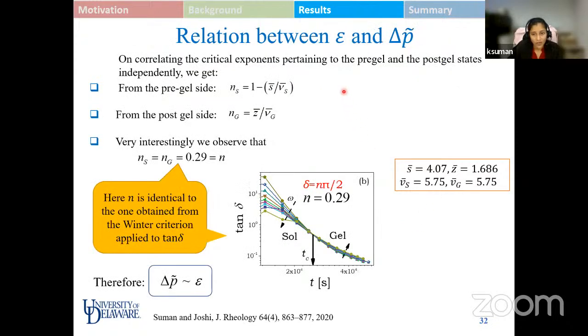With these exponents in hand, we use the laws of linear viscoelasticity, and doing some mathematical calculation, we end up with simple hyperscaling laws, which are relationships between many exponents. So n is the relaxation exponent, and these parameters are the exponents with which the viscosity and relaxation timescale evolve in the pre-gel state. With these hyperscaling laws in hand, we calculate the value of the relaxation exponent in the pre-gel, which is S, and in the post-gel, the G region. And we calculate it to be identical to 0.29, which was independently obtained in the oscillatory experiments. Such a validation of 0.29 using the scaling laws and independent oscillatory experiments confirms that our hypothesis of using time instead of chemical cross-linking extent is validated, and also that the estimation of these exponents is correct.